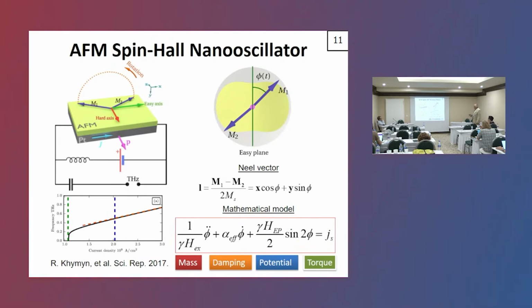This slide simply summarizes our theoretical project of how to create a generator. And a generator can be created by putting a layer of antiferromagnet on a platinum electrode, and then the current flowing in the platinum creates a spin Hall effect, which creates a spin torque on the boundary. So the antiferromagnet should be very thin. And in that case, there will be a tilt of sublattices and rotation of sublattices in the plane perpendicular to the hard axis of the material.